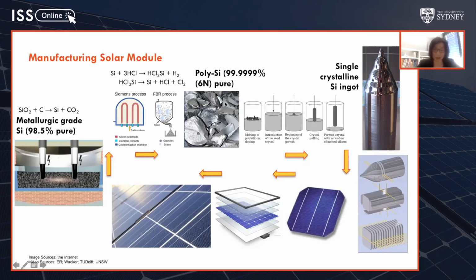After that, we still have to make single crystalline silicon. So we melt the polysilicon and dip a seed crystal into the molten silicon, which is gently pulled up so that the melt solidifies on the seed crystal and adopts the crystal orientation of the seed. We have an ingot, and then we slice the ingot into wafers, which are then textured to deliberately produce a velvet finish, so you don't get a mirror finish that reflects light too much. You also have to dope the wafers with phosphorus or boron to form the PN junction, which is the basic building block for optoelectronic devices. The PN junction is important to separate electrons and holes to the respective polarity electrodes.